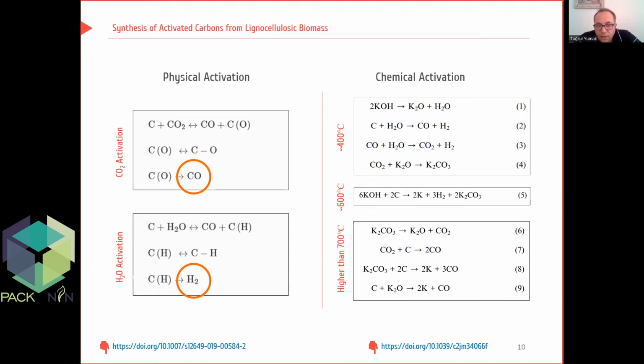In the KOH activation, KOH, potassium hydroxide, dehydrates to transform into potassium oxide at almost 400 C. Then the carbon is consumed by the reaction of carbon and water with the emission of hydrogen. The potassium carbonate is formed by the reaction of potassium oxide and carbon dioxide, which is produced in equation 3 on the right side.